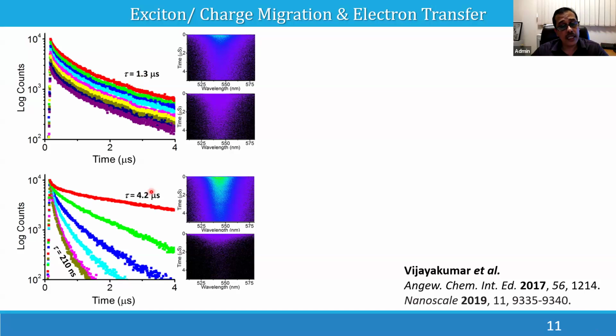And interestingly, the nature is different. In the film, even with a very, very small quantity of C60, there is a significant decrease in the lifetime. In the solution, the lifetime is not decreased, only the fluorescence intensity that you can see here decreased. Okay, but in the film, not only does the intensity decrease, the lifetime also decreased from 4.2 microsecond to 210 nanosecond.